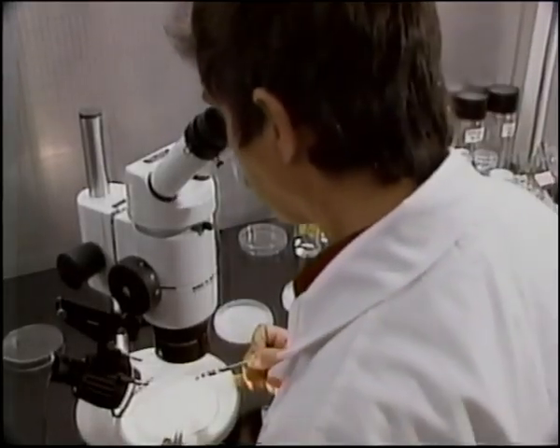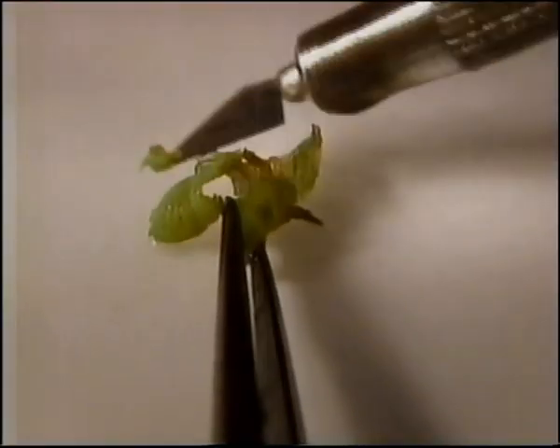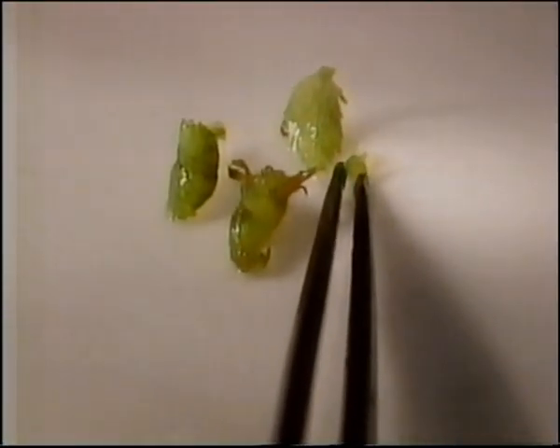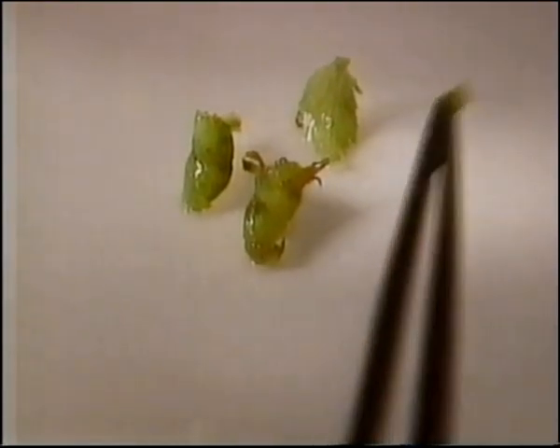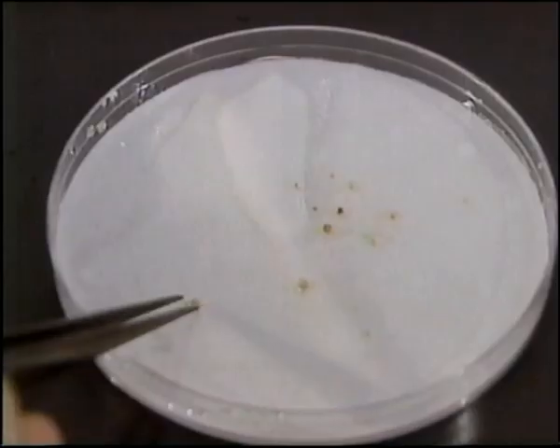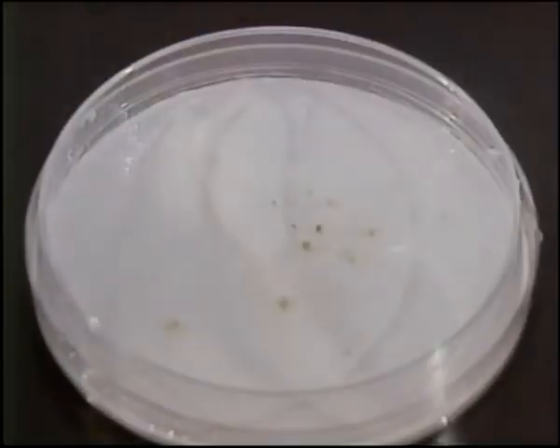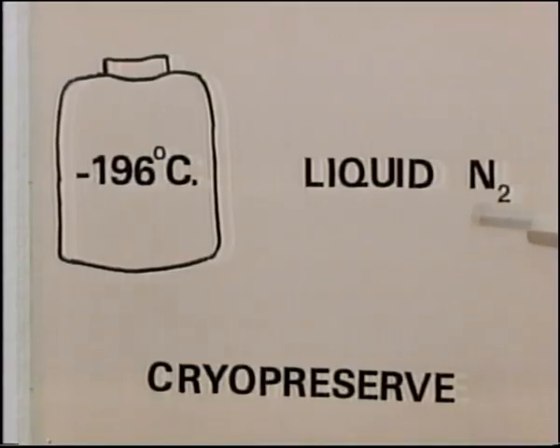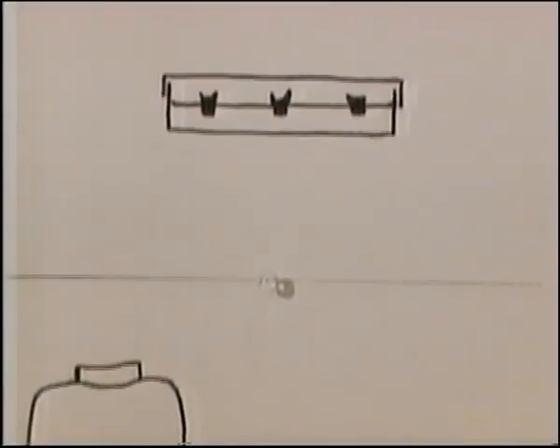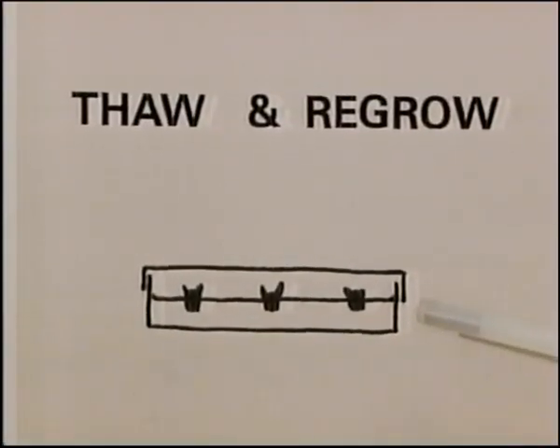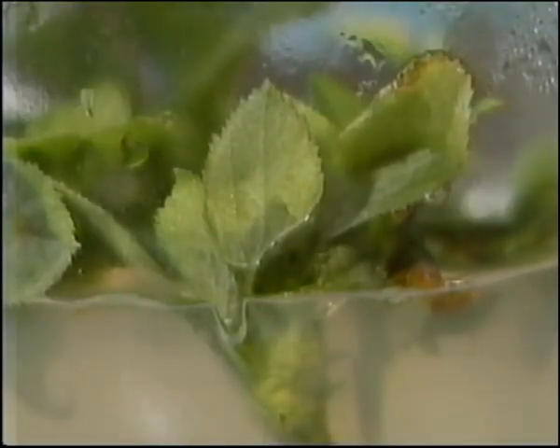After this, the meristem, which is a 1/2 millimeter section of the growing point of the shoot, is isolated and treated in a cryopreservative solution. The meristem with the cryoprotectant is frozen, in this case at a much more rapid rate, from 1/10 to 1 degree centigrade per minute to -40, and then plunged from -40 into liquid nitrogen. Following the storage in liquid nitrogen, the meristems are retrieved, placed back on an agar media, grown under controlled conditions, and we are now trying to recover whole plants following this stage.